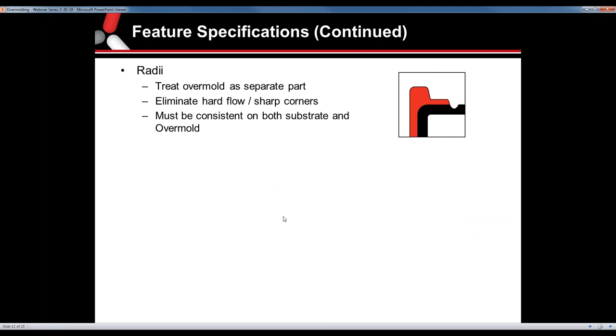These materials for injection molding do not like sharp corners — do not like 90 degrees or any type of abrupt transitions. The material flows much better if you have a smooth transition when possible in your design. Radii are always recommended in any area; no sharp corners. Keep a nice nominal wall thickness. That wall thickness is really dictated by the material itself — some materials flow better through thinner areas, some do not. That's something you have to be cognizant of as you're designing your parts.